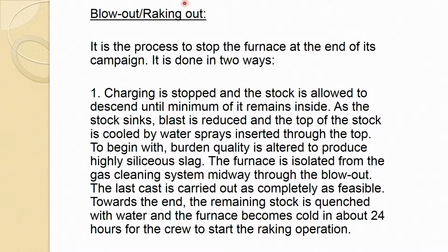So, this raking out is coming from this raking operation when the personnel start this operation. Here you use the water spray to cool it down, and of course, again use highly siliceous slag towards the end of it, as we do in the blow in at the starting. Here towards the end you use the siliceous slag which can easily pass through, and the furnace is isolated midway through that.